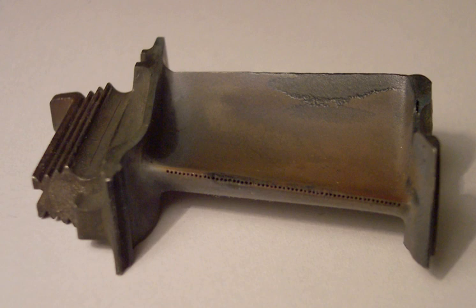Topic: superalloy processing. The historical developments in superalloy processing have brought about considerable increases in superalloy operating temperatures. Superalloys were originally iron-based and cold-wrought prior to the 1940s. In the 1940s, investment casting of cobalt-based alloys significantly raised operating temperatures. The development of vacuum melting in the 1950s allowed for very fine control of the chemical composition of superalloys and reduction in contamination, and in turn led to a revolution in processing techniques such as directional solidification of alloys and single crystal superalloys. There are many forms of superalloy present within a gas turbine engine, and processing methods vary widely depending on the necessary properties of each specific part.